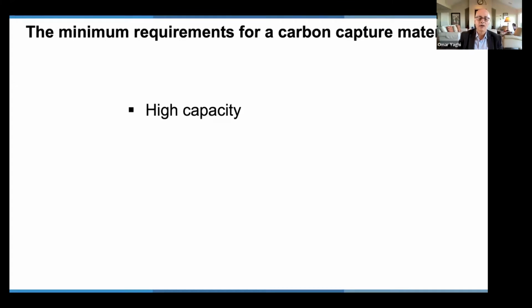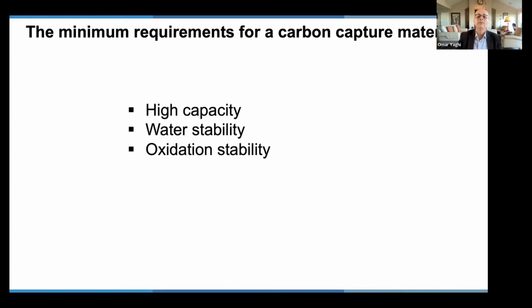The minimum requirement for a material to be a good CO2 capture material is that first you need high capacity, so that when you're cycling, you're not doing so many cycles to achieve the desired CO2 capture. You need materials that are water stable, because there is water in the atmosphere, there is water in flue gas, and you need a material that is not going to oxidize because there is oxygen present in all these binding events, and you need the material to be cyclable.